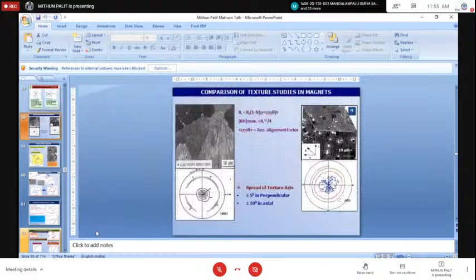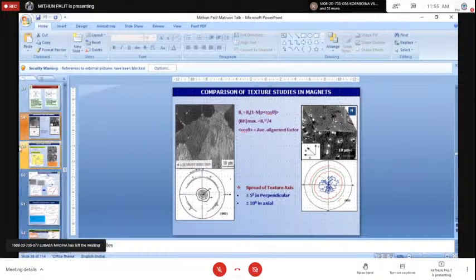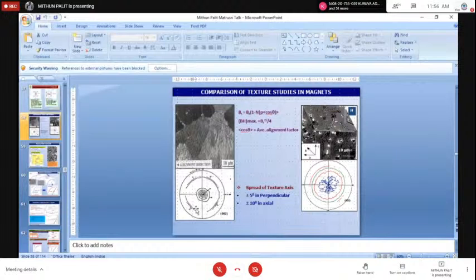These are some of the microstructures, and this is called the X-ray pole figure. Basically, it tells how strongly the material is oriented. For example, if in this particular magnet we want all the material to be oriented along the c-axis of the crystal, then when we talk about the c-axis pole figure, if the contours are very close to the origin of the pole figure, that means the orientation is stronger. If it has some scatter, some spread, then the orientation is not very strong.